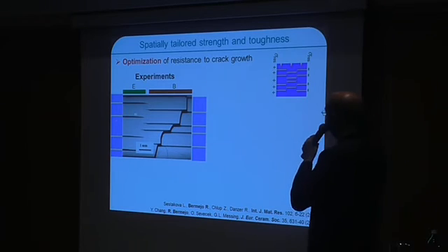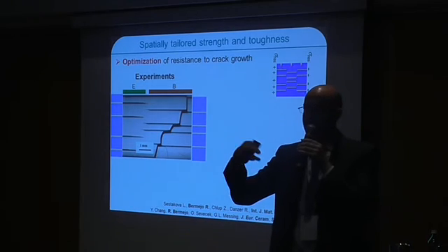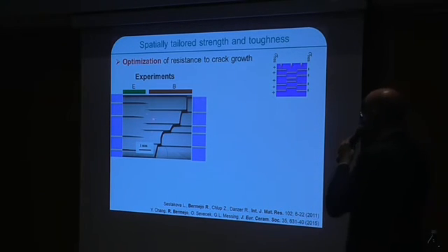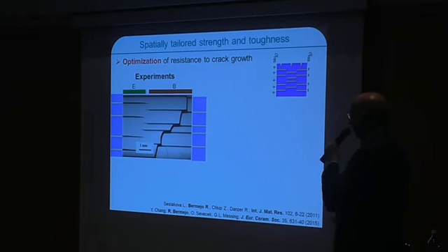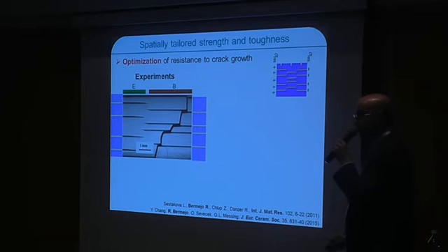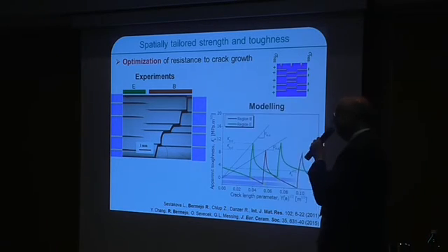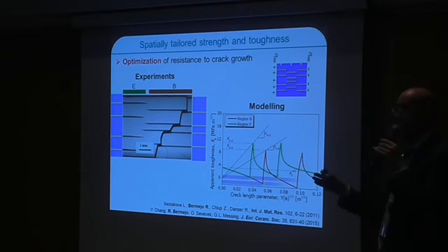We could observe that in all regions, we get some crack arrest, like in the case of this thermal shock or bending, because we have very high compressive stresses. But what was very interesting was to see that in this particular disposition, the fracture will always occur through this central region here, as you can see. This is easy to understand when we apply our model, and we model the crack resistance of the different regions. And we understand that there are somehow weak regions and strong regions from a mechanical point of view.